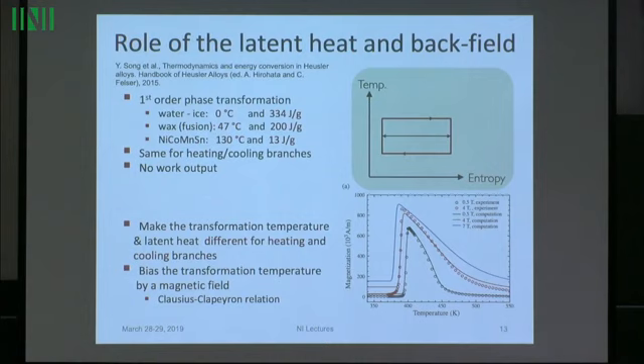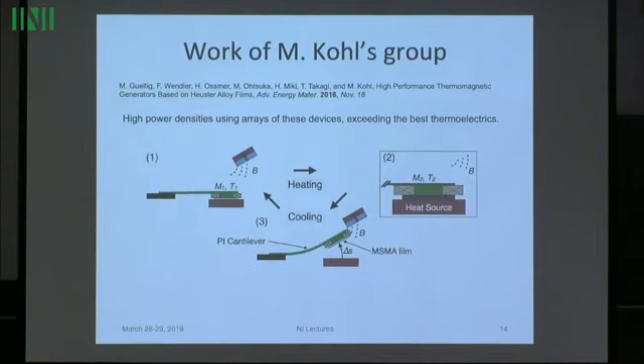Also, in the meantime, we kind of soured on this method for another reason. Remember, I said that there's this shape effect. You want the big dM/dt to give you a big dB/dt. You don't want it all to go into dH/dt, because that does nothing. And I mentioned that depends on the shape of the specimen through the last term, the demagnetization energy term in micromagnetics.